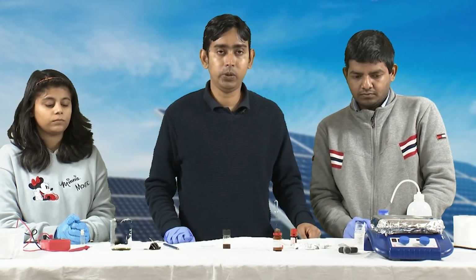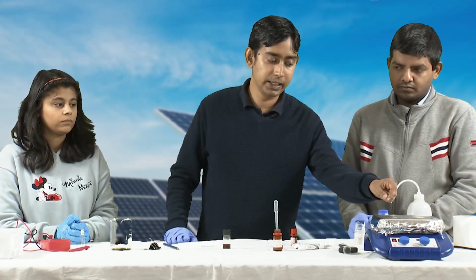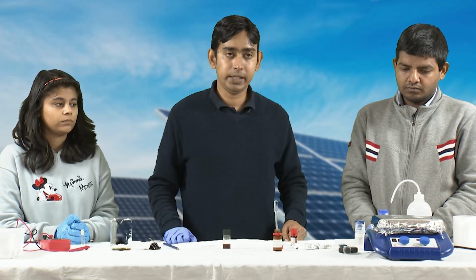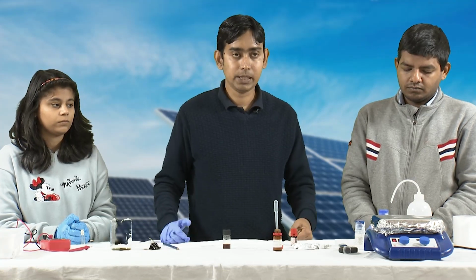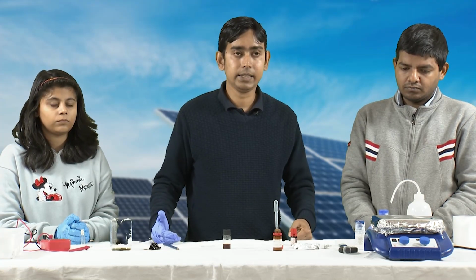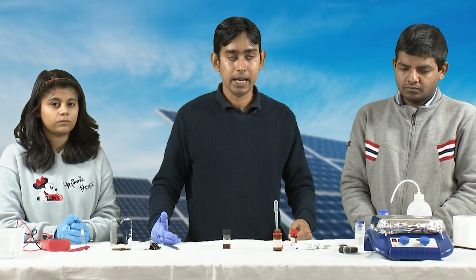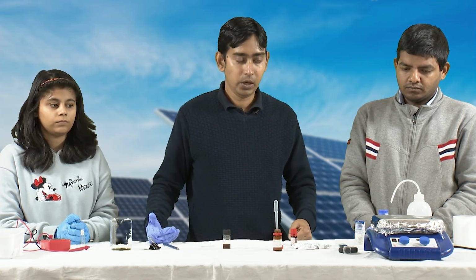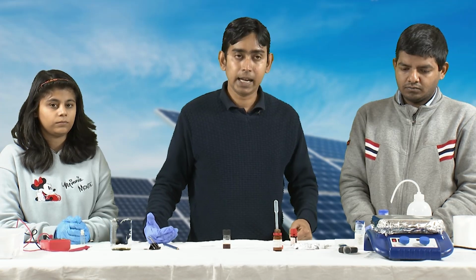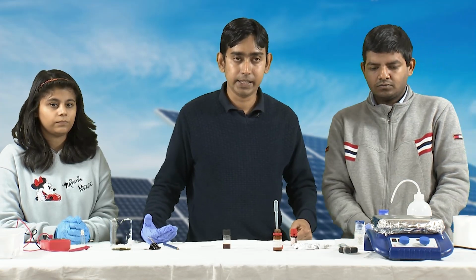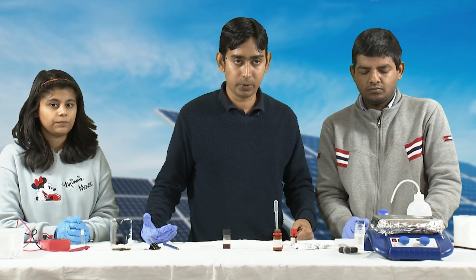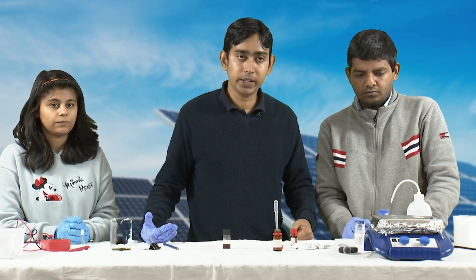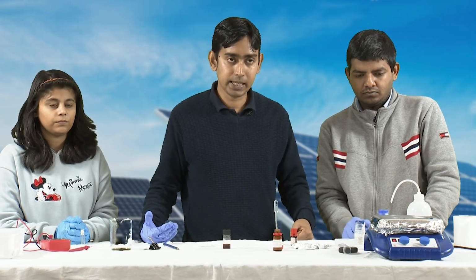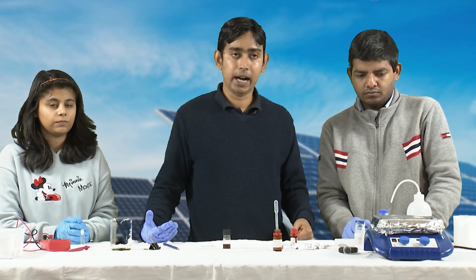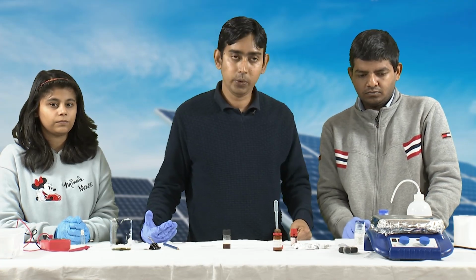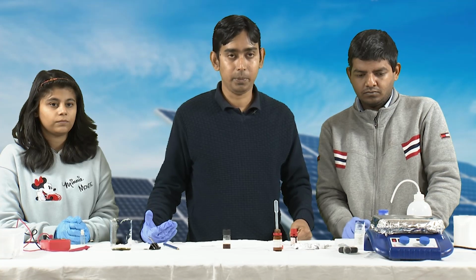So, usually what we do is we take this titanium dioxide coated glass substrate and put it in a muffle furnace, which is a specially designed furnace, and we heat the substrate at 450 degrees Celsius and keep it for 3 to 4 hours. Within 3 to 4 hours, the titanium dioxide not only changes crystal phase, it also becomes a more mesoporous structure. But here we are doing a low temperature sintering for demonstration purposes. So, here we are trying to heat it at 120 degrees Celsius, and we wait to see how much color change we can see from here. Okay.